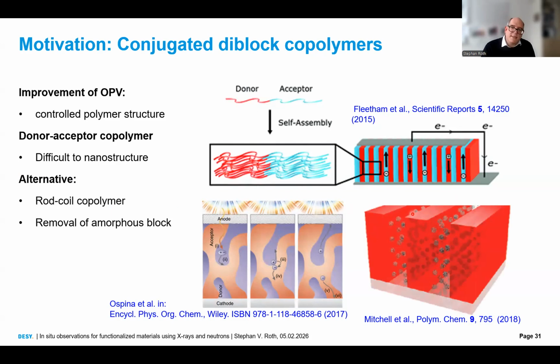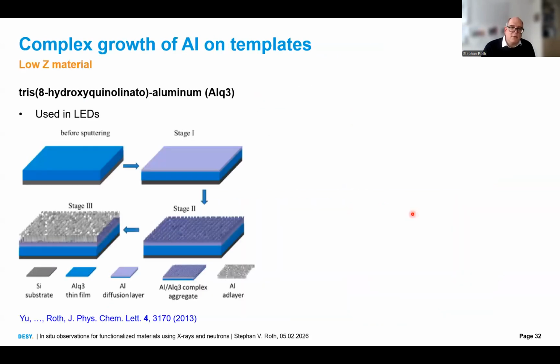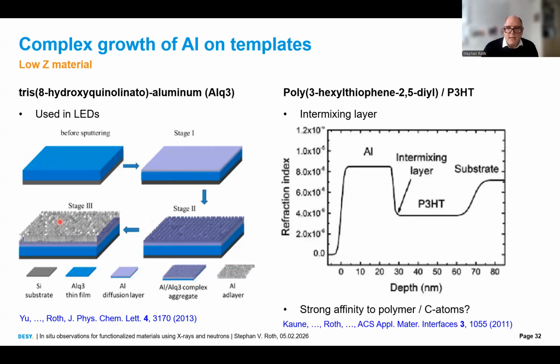And our question is how does the electrode grow on this? And what's the cheapest electrode you can do? It's aluminum. Gold is expensive, silver semi-expensive, but heavily used by the semiconductor industry, so we use aluminum. We did this indeed in the past for looking into electrodes for LEDs. We deposited aluminum on aluminum quinolate, and we could follow in all details the stages of growth of the aluminum layer.